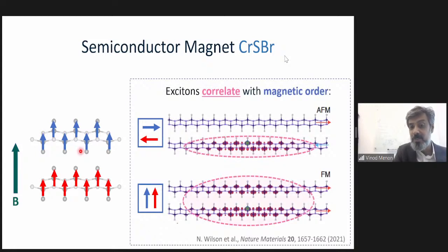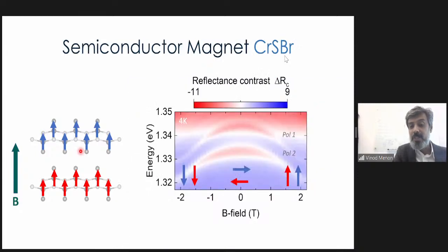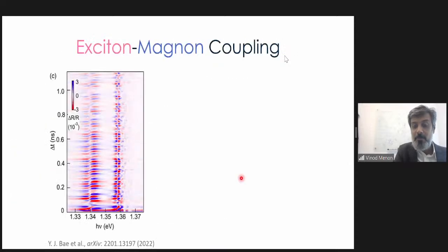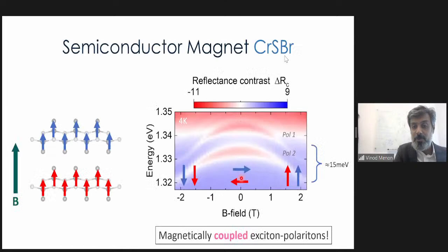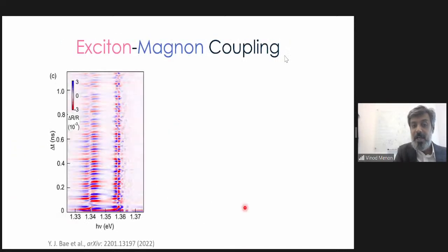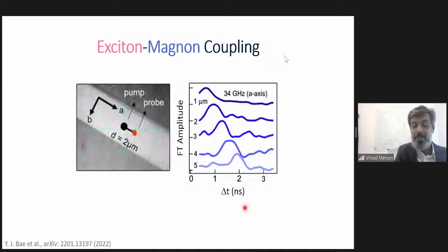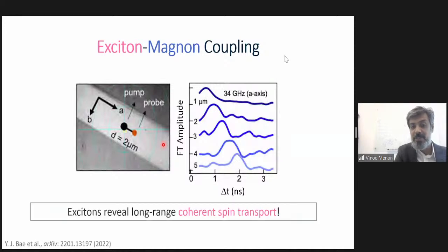So clearly the excitons in this material correlate with the magnetic order. And if you look at the reflectance of the excitons, you start with zero field and you start changing the field, everything redshifts, but it also saturates, where it becomes ferromagnetic pointing down, ferromagnetic pointing up, and at zero field, anti-ferromagnetic coupling. So what this proves is that you can create magnetically coupled exciton polaritons. That's really the key here. And I'm going to skip this slide and just point out that you can actually see exciton-magnon coupling. You can see long-range propagation of magnons in these systems. And so you could envision these for coherent spin transport.